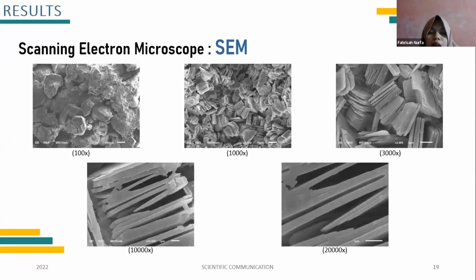Next is SEM results. At a magnification of 100 times, it can be seen that the surface of the powder sample under examination consists of a number of solids in the form of grains. This is quite obvious and can be related to the microCT results that the sample consists of grains. At magnification 1000 times and further, it shows more deeply the morphology of these grains.